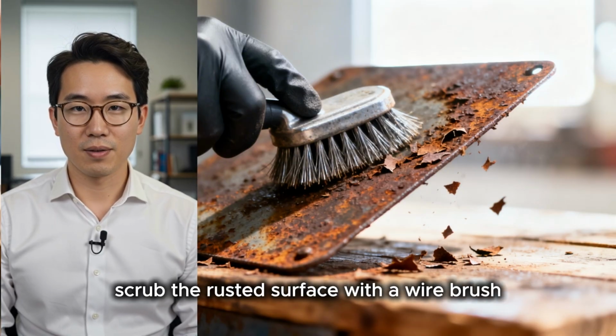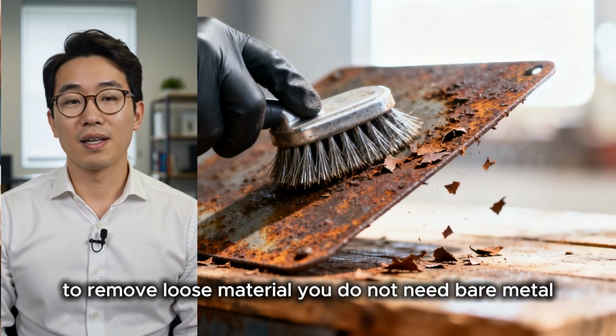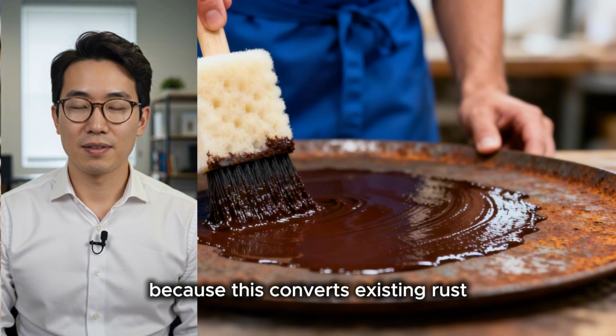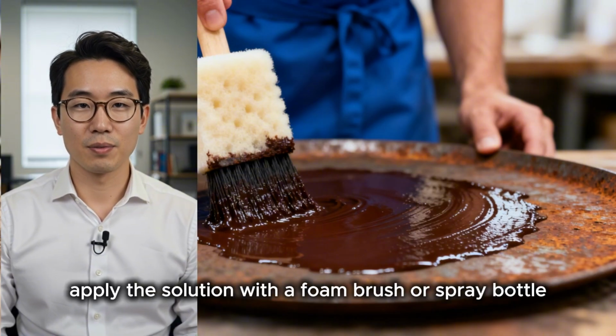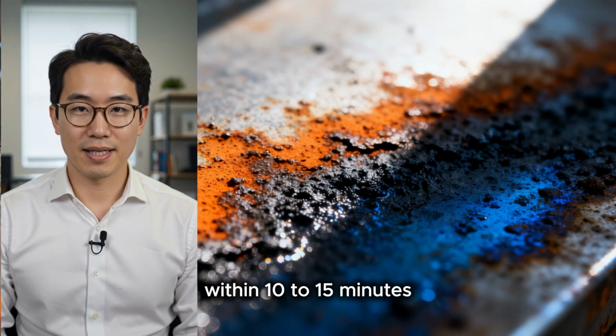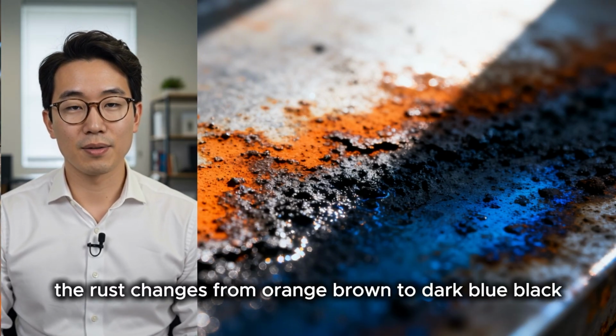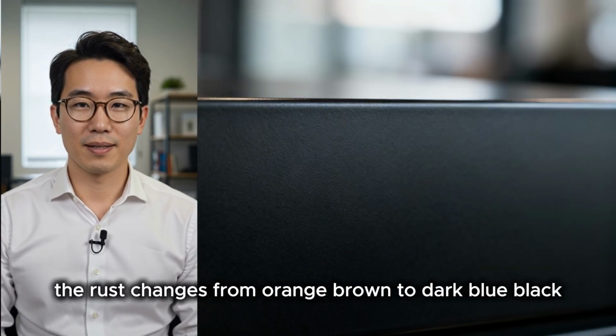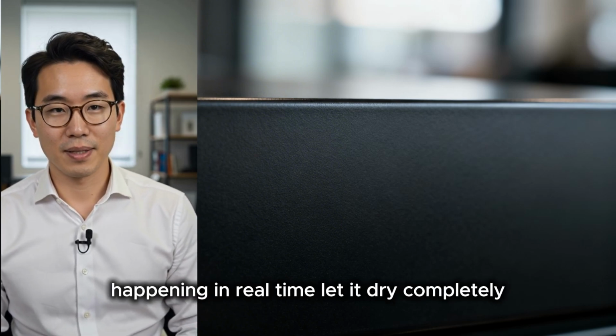Scrub the rust surface with a wire brush to remove loose material. You do not need bare metal because this converts existing rust. Apply the solution with a foam brush or spray bottle. Within 10 to 15 minutes, the rust changes from orange-brown to dark, blue-black. That color shift is molecular conversion happening in real time.